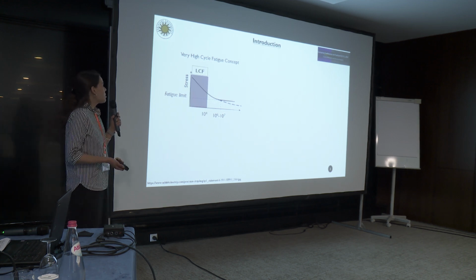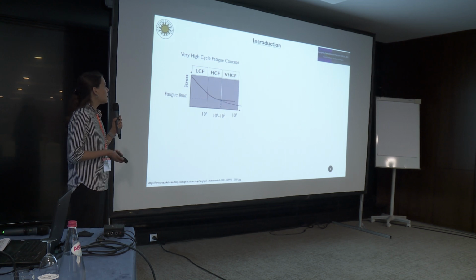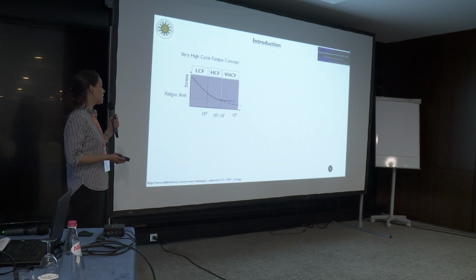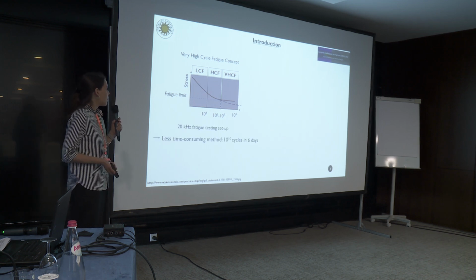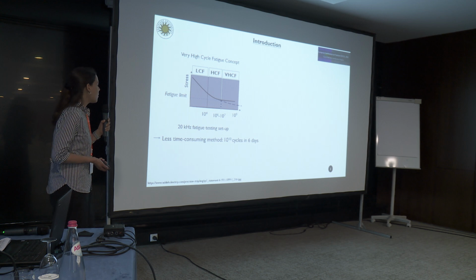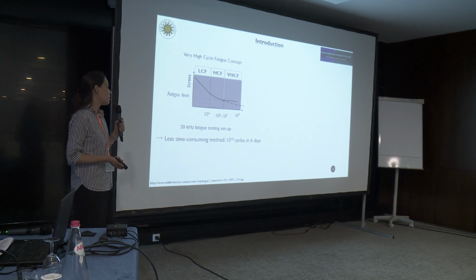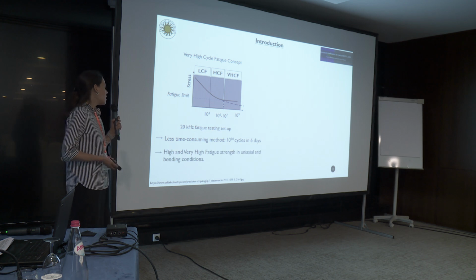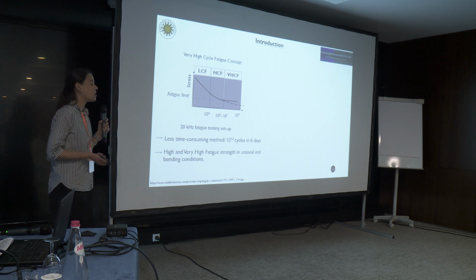So a distinction between low cycle fatigue, high cycle fatigue, and very high cycle fatigue could be made based on the number of cycles completed. With the ultrasound 20 kHz fatigue testing setup, we are speaking about a less time-consuming method, since we can achieve 10 to the 10 cycles in 6 days, and we can have high and very high cycle fatigue strength in both uniaxial and bending conditions.